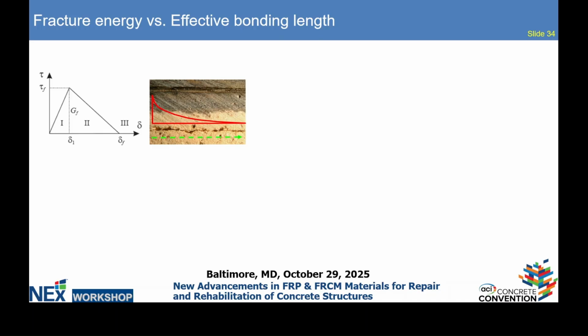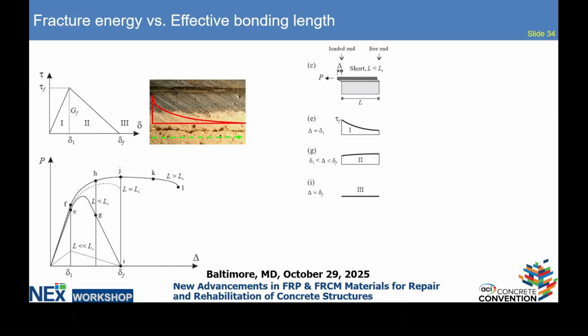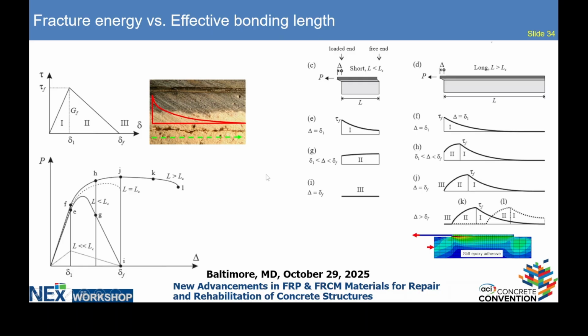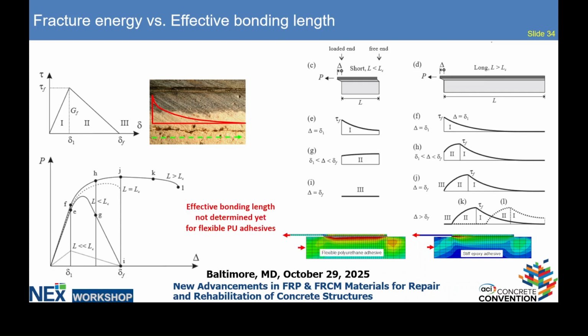Go to fracture energy. Typically, using FRP, we assume that the substrate is the more critical element, yeah? So the stress concentration is cutting that. When we do not have effective bonding length, in this case we have this curve. When we reach the effective bonding length, for epoxy it is quite short, we fully use the properties of the system. But in the case of flexible polyurethane adhesive, we haven't found the effective bonding length yet.